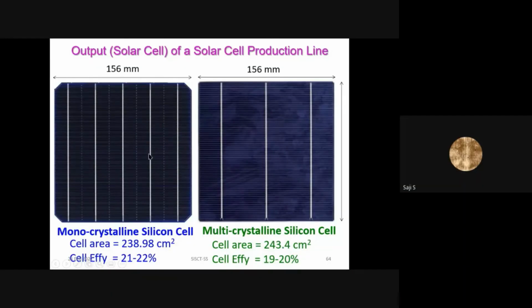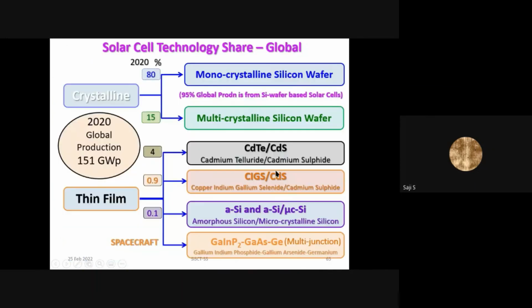So this is the output of the solar cell manufacturing line, which is a monocrystalline solar cell and a multicrystalline solar cell. It would be either one of these, not both from the same line. The monocrystalline solar cell, as I said, has a higher efficiency of 21 to 22%. Multicrystalline slightly less because of the grain boundaries, 19 to 20%.